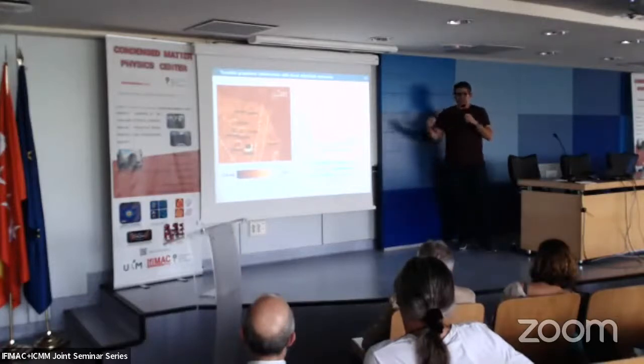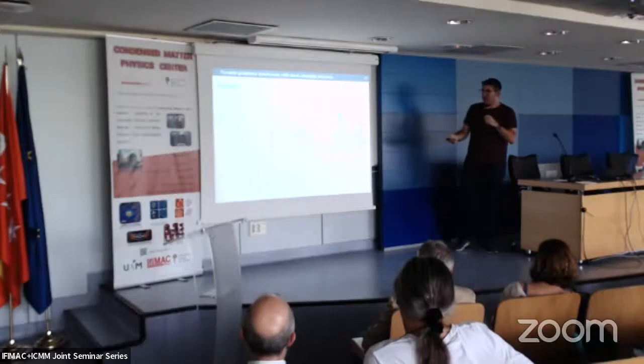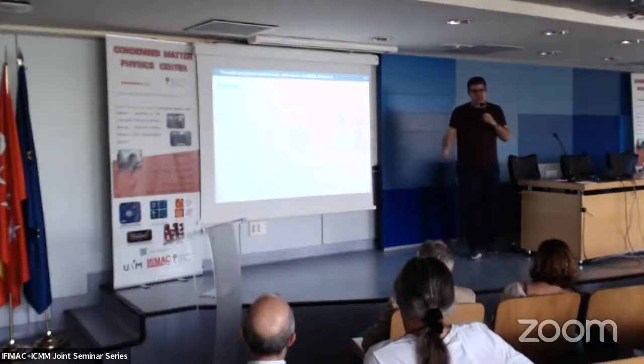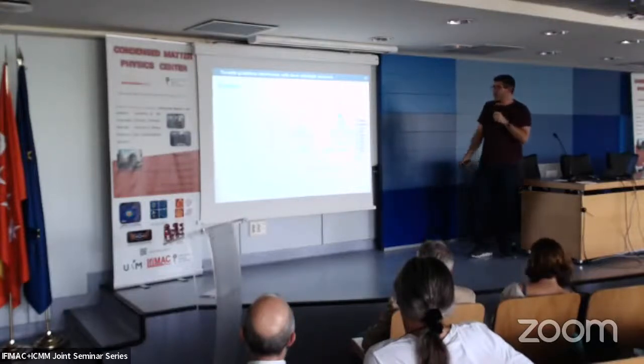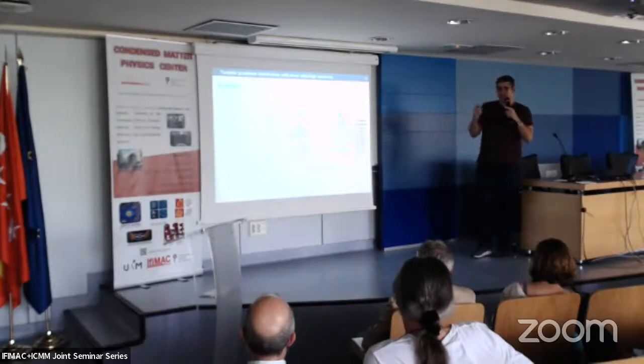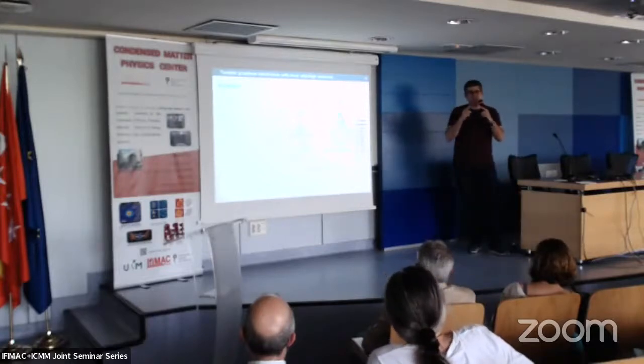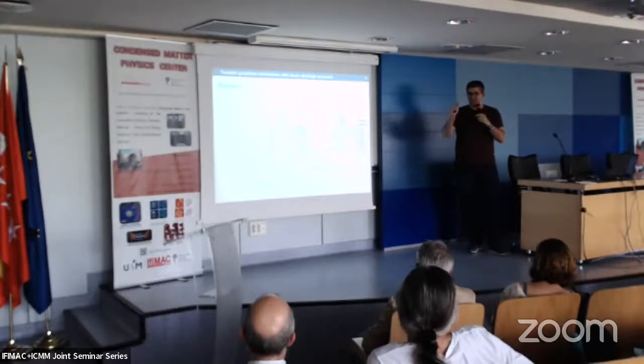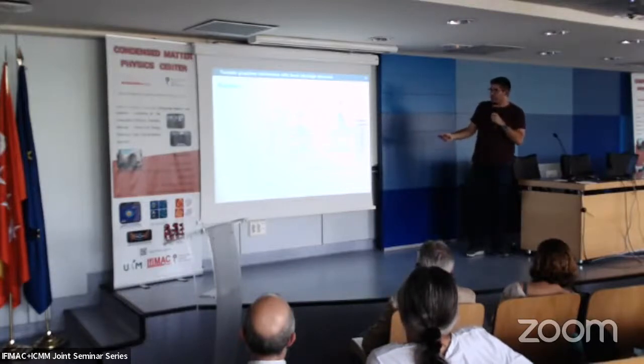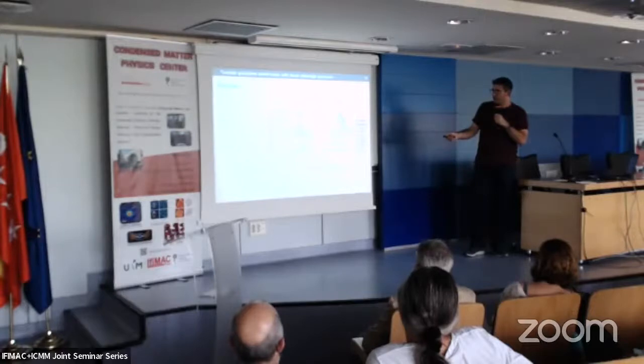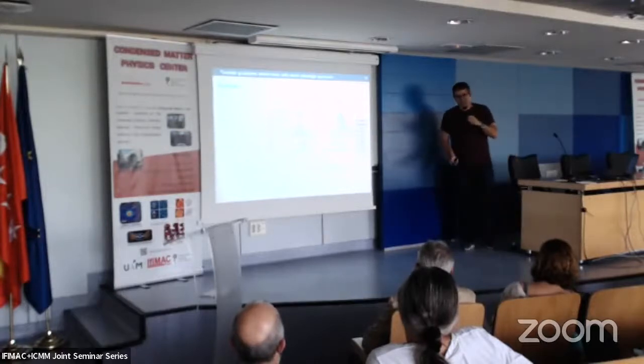So in order to study the level of doping in those areas, we brought our samples to a micro-Raman facility, the one here in Donostia, and we took spectra. The spot in that Raman is like 200 to 300 nanometers, so we can take spectra at very precise locations and even take maps. If we take a spectrum in each of the modified areas, we can see how these G and 2D peaks change. They shift, they change the width, they also change the intensities. So all this is related to the doping level.